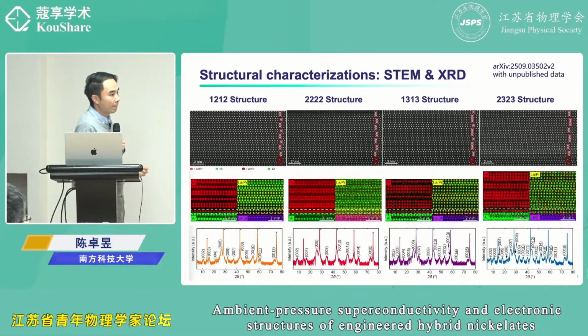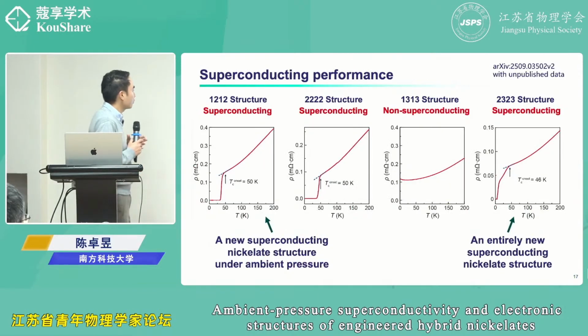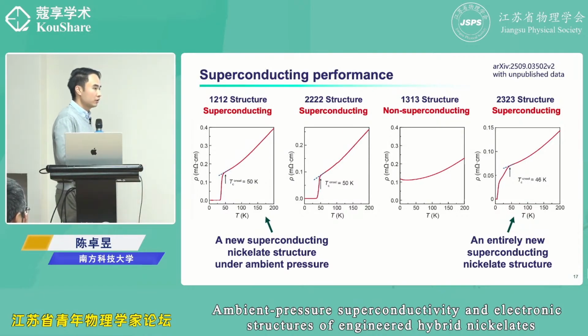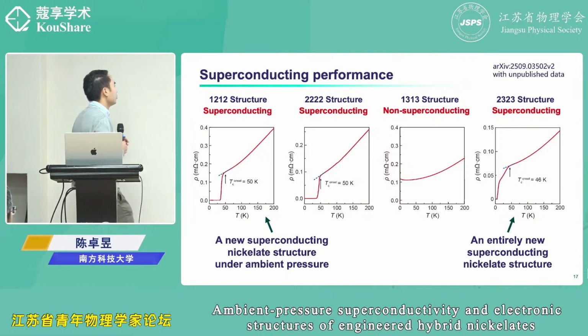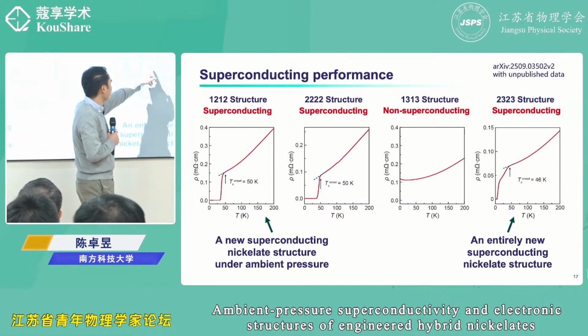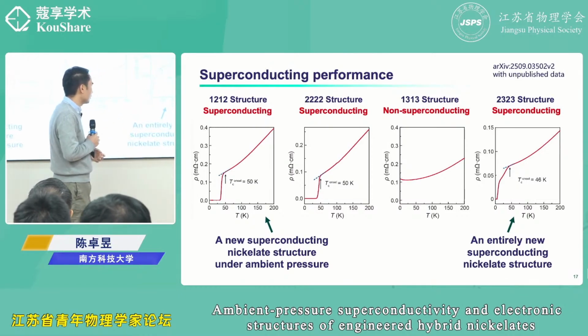So far only 3 show superconductivity: 1-2-1-2, 2-2-2-2, and 2-3-2-3. And 1-3-1-3 is not superconducting. Yes, that's a very good question. For these 2 structures, after growth optimization and all the process optimization, we can get a pretty good single transition. For this 2-3-2-3, at least for now, many of our samples show two transitions. Another interesting thing is the TC for the first one is about 45 to 50, but the second one is always between 10 and 20.